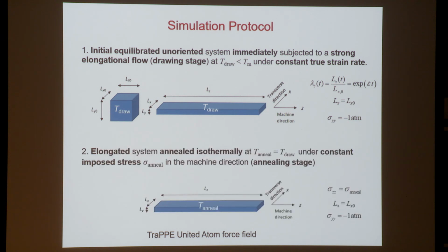As regards now the annealing simulation, we take this film that resulted from the drawing, we keep it under constant stress in the Z direction, the sigma annealing, and we again keep the X direction constant, and the stress in the Y direction is -1 atmosphere.